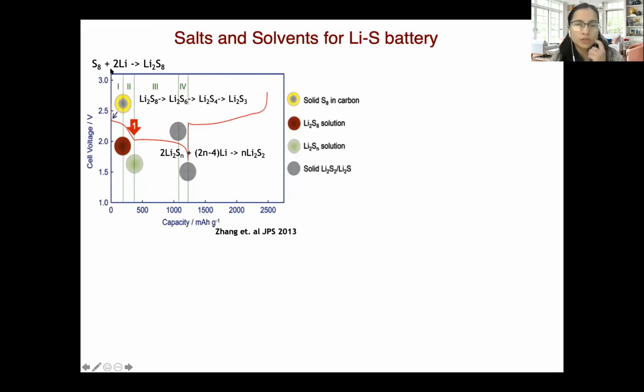The first region is where elemental sulfur reacts with lithium to form Li2S8. And the second region is where we form a bunch of different lithium polysulfide species. I would like you to notice here that there is a sharp voltage decline in the second region. And I'll talk about that in a minute, of why we think that there is the sharp voltage decline in the second phase.